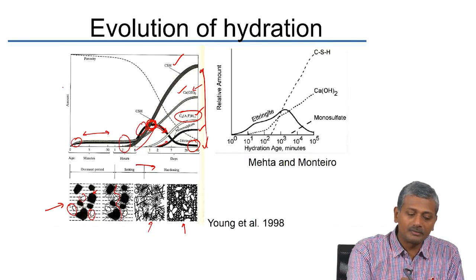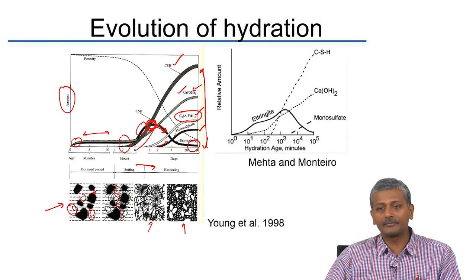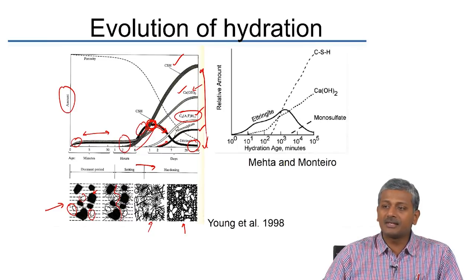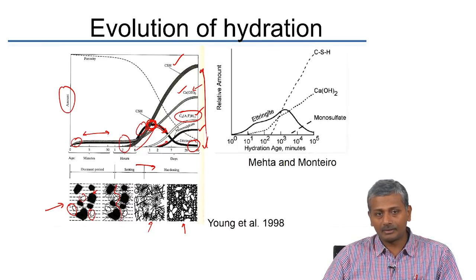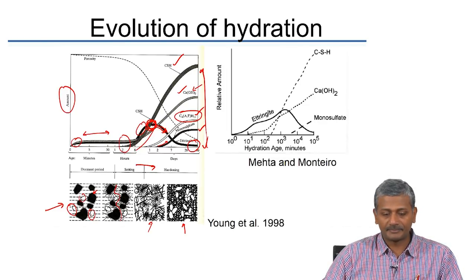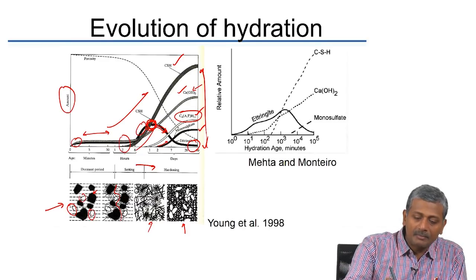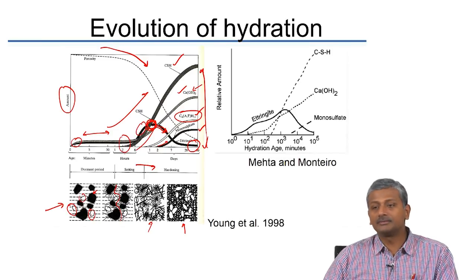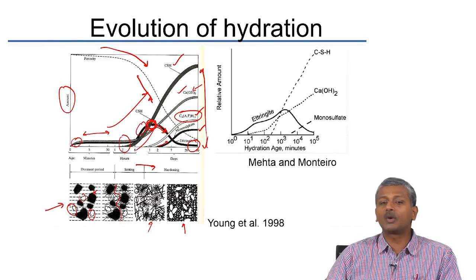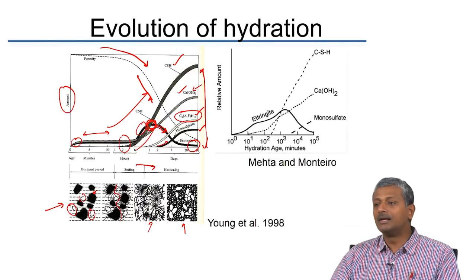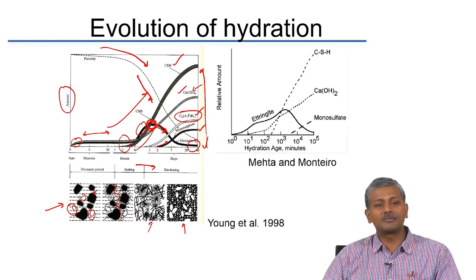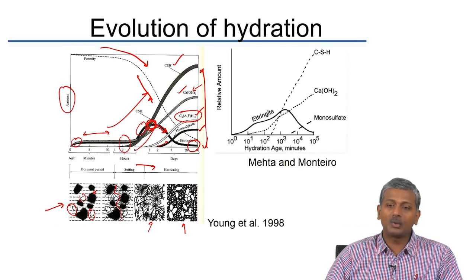The representation does not show exact proportions. Most of the cement paste is calcium silicate hydrate, forming nearly 50–65% by volume. Calcium hydroxide forms about 15%. The remainder is aluminate and monosulphate phases. As hydration products form, porosity gradually declines — rapidly during the quick hydration phase, then slowing beyond 7 days. In modern cements, nearly 90% of 28-day strength is reached at 7 days.